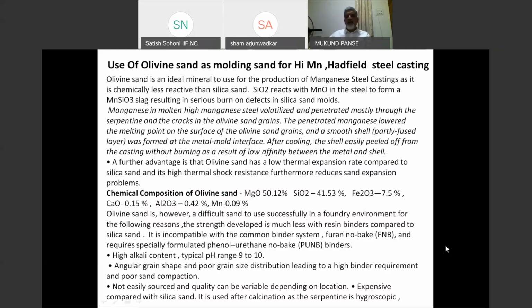It has high alkali content and it doesn't go well with certain resins. You have to choose the resin sand mixture properly if you are using it. It is only used mainly in manganese steel because silica sand grains react with manganese steel and you get a very bad surface. The grains of this are angular.